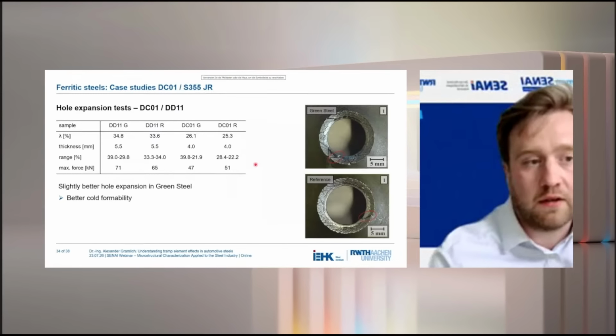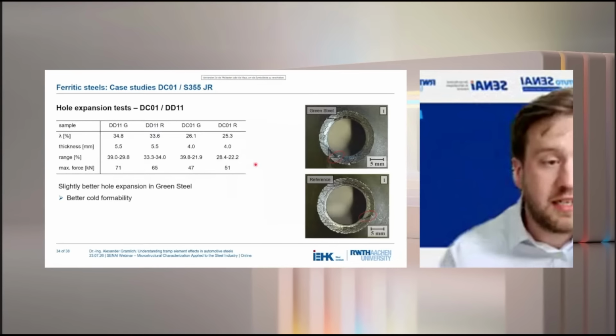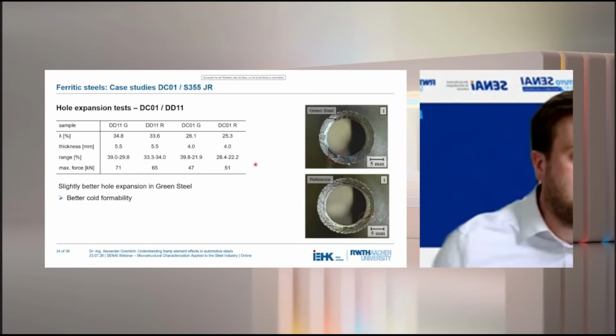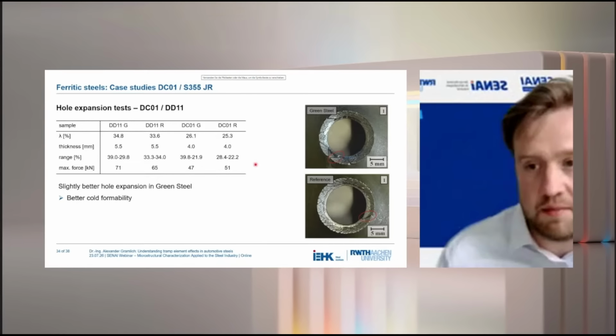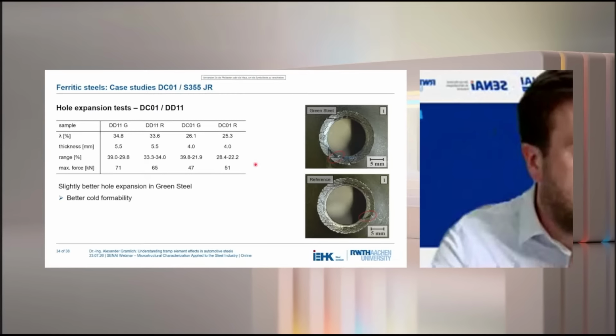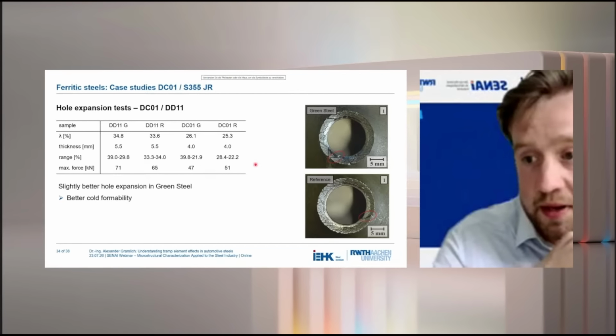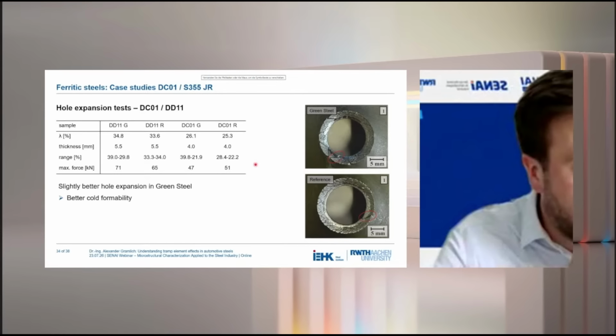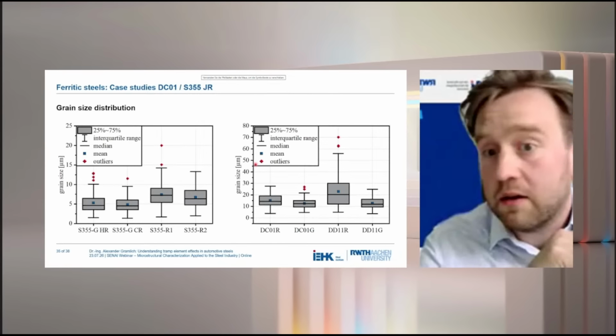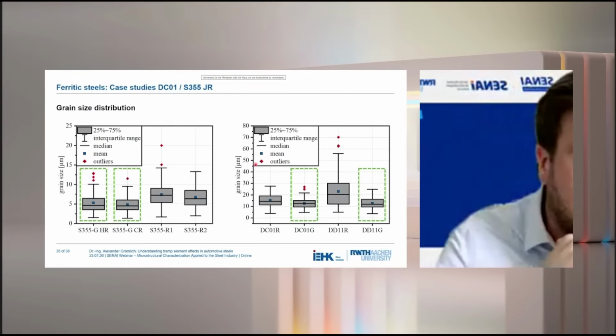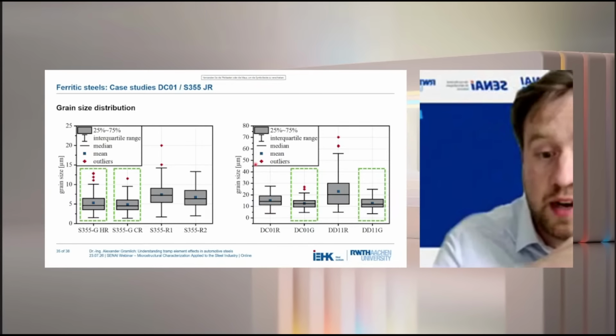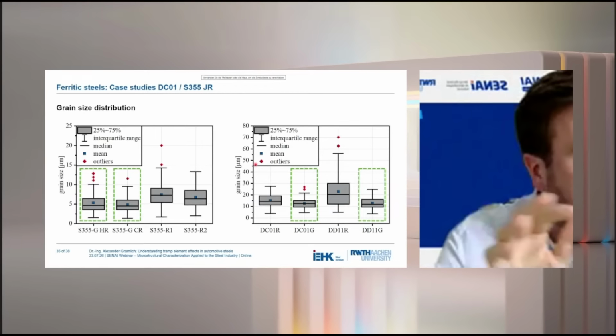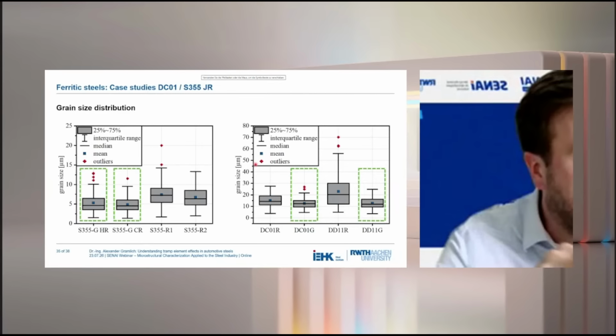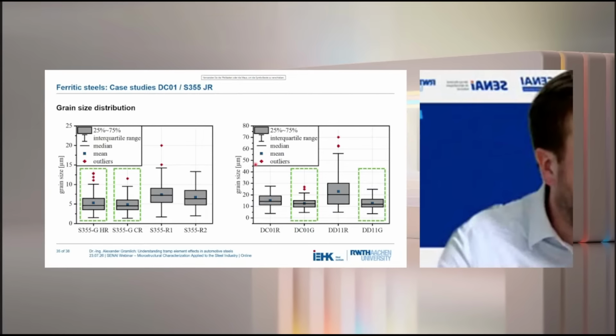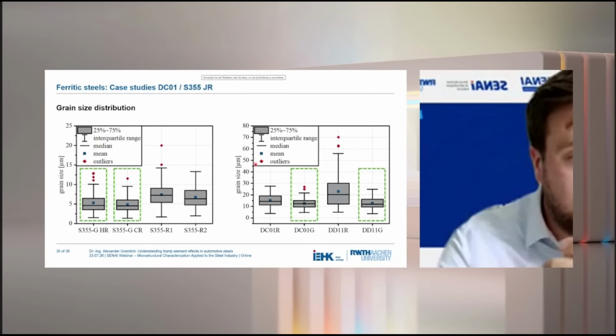However, when we looked then at the deep drawing steel, we could see that here our hole expansion ratio was increased, even with the higher strength and the introduced tramp elements. The reason for this was then connected basically to the microstructure. We did a thorough investigation of the grain size distribution, and what we could find out for both steels is that the green steel variants had a much smaller grain size due to the solute drag effect of the tramp elements, which prevent basically the coarsening of the ferrite during the batch annealing.